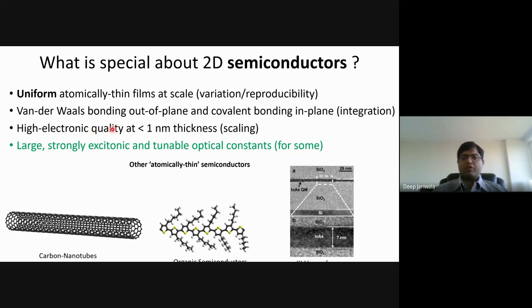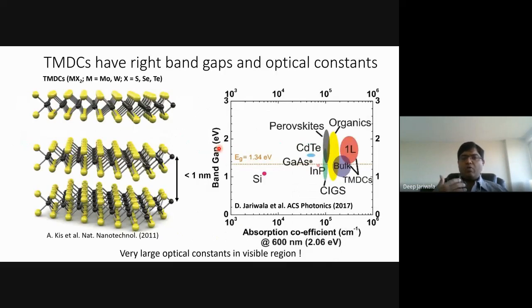But from an optics or photonics perspective, the reason these 2D semiconductors are quite interesting and unique is because of this last point written in green: they are strongly excitonic, and they have very large, tunable optical constants, at least for some of the 2D materials that I'm going to talk about. What do I mean by optical constants? I mean refractive index and extinction coefficient or absorption coefficient. These are two fundamental optical constants of every material, the real and imaginary part of refractive index, or epsilon 1 and epsilon 2. And so let's look at how these materials look structurally, and how their optical constants look.